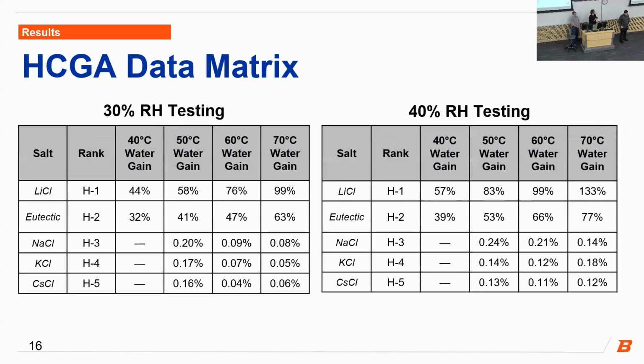Moving forward, we have our humidity-controlled gravimetric analysis data tables with our 30% relative humidity testing on the left and our 40% on the right. These salts were hygroscopically ranked H1 through H5, with H1 being the highest rate of hygroscopicity. As you can see, for the lithium chloride and the eutectic, they are above their deliquescence point, which is why their water uptake is significantly larger than the other 3. And once they're above their deliquescence point, their behavior is as you would expect. With increasing temperature and humidity, they have a substantial increase in the weight gained.